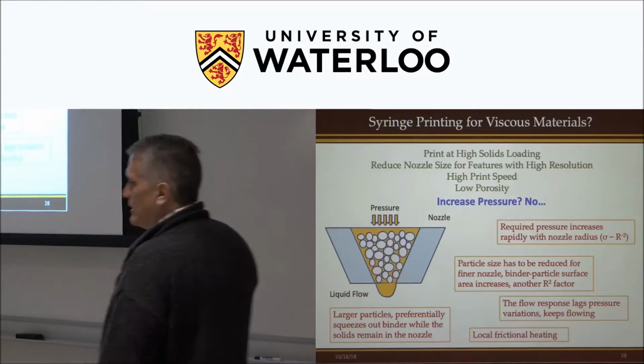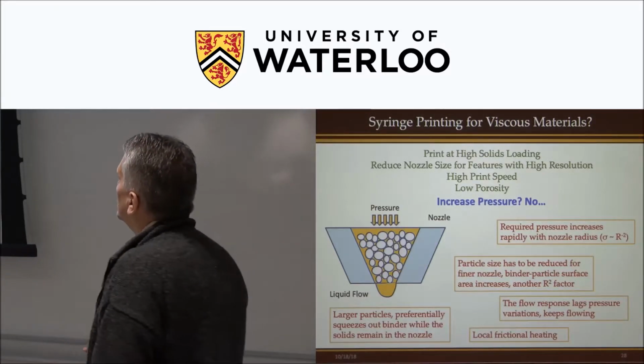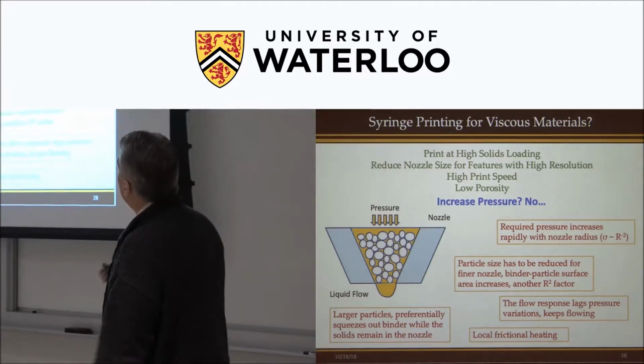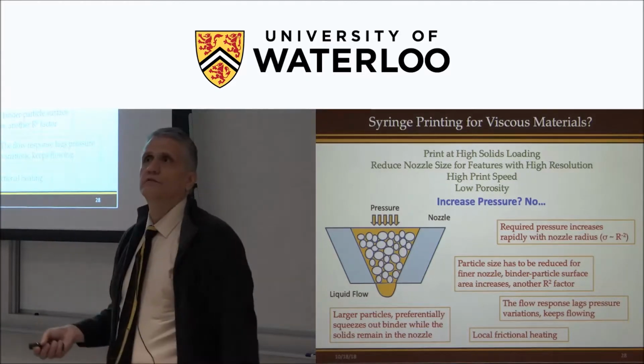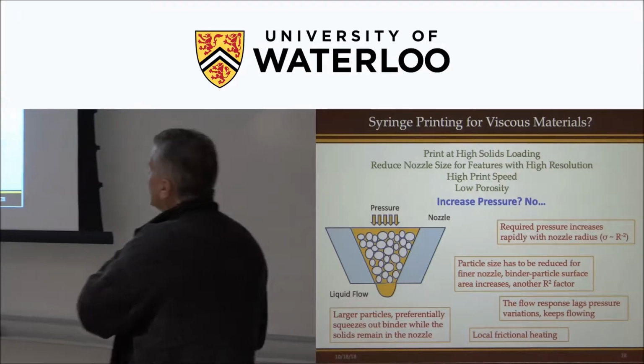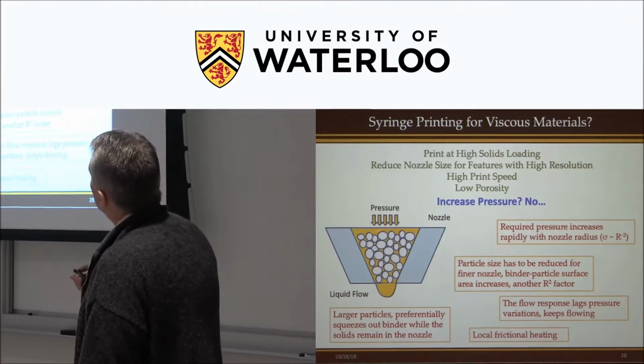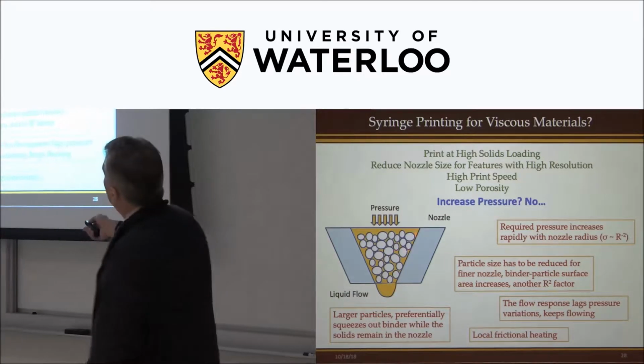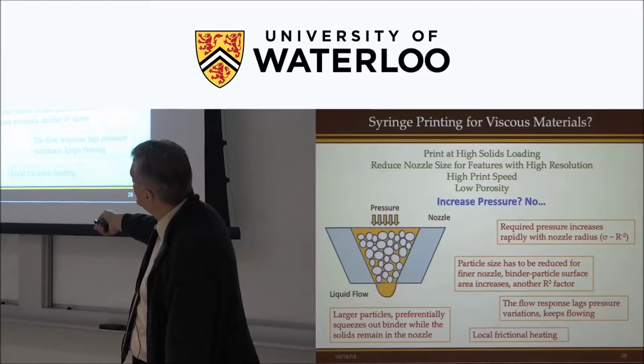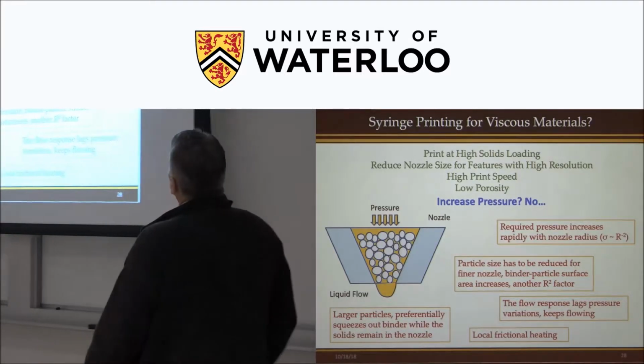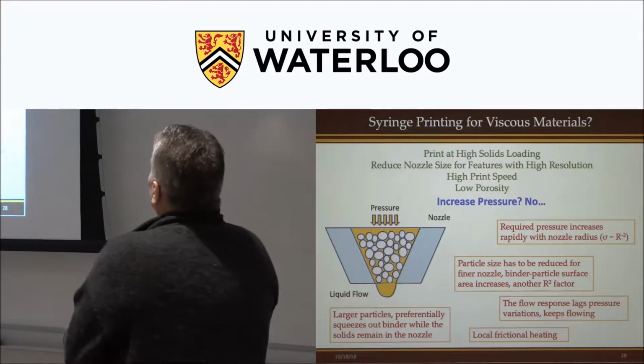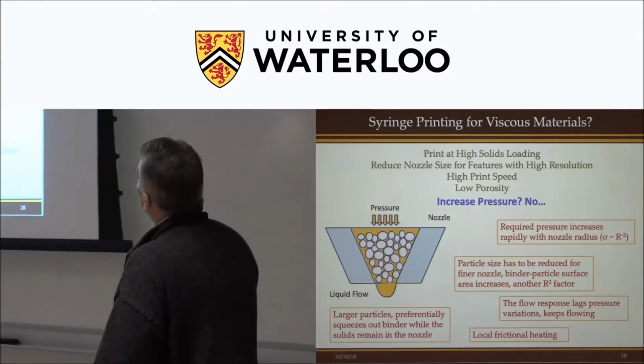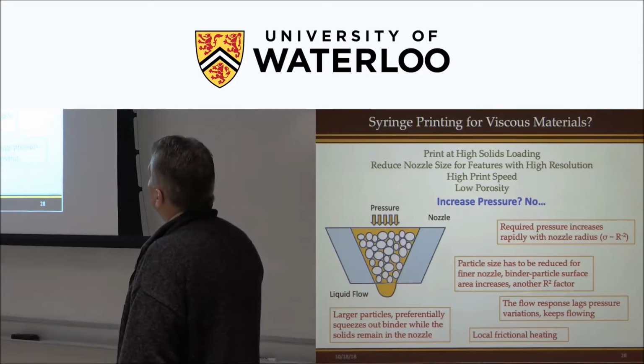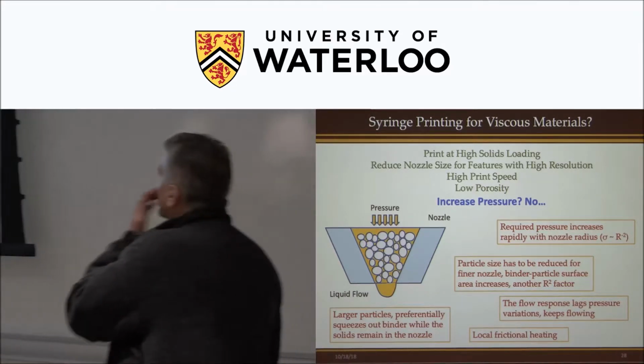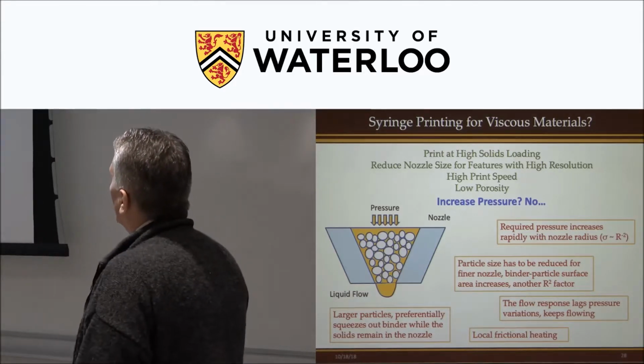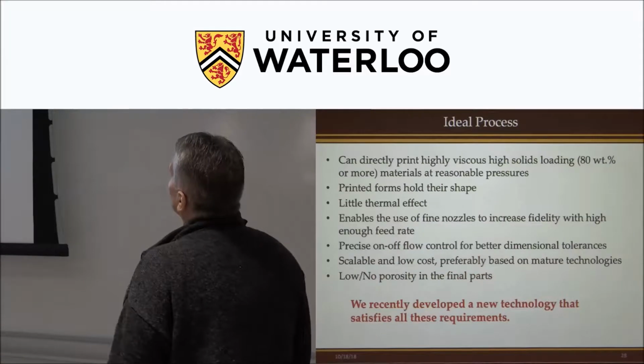So you would think, well, if we're thinking about printing this viscous material with a nozzle, maybe we'll just increase the pressure. But if we increase the pressure of a highly solid loaded viscous material, those particles can bind together and the pressure could succeed at extruding just the binder, so it de-wets. And that rapidly increases as you go to smaller and smaller nozzles. And you have to have smaller particle sizes for finer nozzles, and there is local frictional heating. There's all sorts of problems.